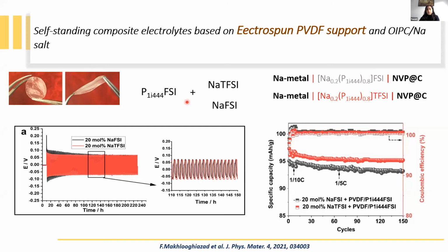So we characterized them thoroughly based on NMR characterization, thermal phase behavior, and ionic conductivity. And here is the cycling performance of these two composites, both in sodium symmetrical cell and sodium full cell, showing excellent long-term stability. But it is interesting that the composite based on mixed anion outperforms the composite that has only FSI anion. Based on our NMR characterization and thermal phase behavior, we found that it's because of the interaction of TFSI anion with PVDF, which makes an amorphous phase that has a higher ionic conductivity than the crystalline phase that the FSI system has.